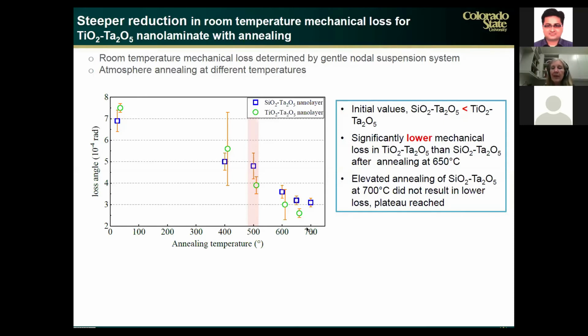So again, what these results identified is that yes, the mechanical loss decreases with annealing, but the mechanisms that are responsible for this reduction in mechanical loss may be very different. We obtain the lowest mechanical loss, or loss angle, in the silica tantalum nanolaminate.